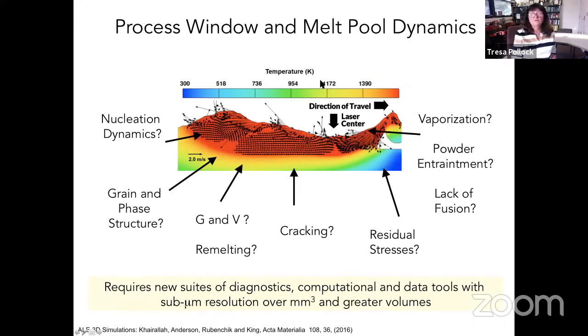And so really what one has to pay a tremendous amount of attention to is what happens in this melt pool at the point where either a laser beam or an electron beam interacts with the material. So today I will focus on both laser powder bed and electron beam melting, and neglect other processes such as wire additive manufacturing, for example. So in both the laser and electron beam processes, you have this melt pool that's maybe a few hundreds of microns in extent, in width and depth. And what are all the things that you have to worry about?